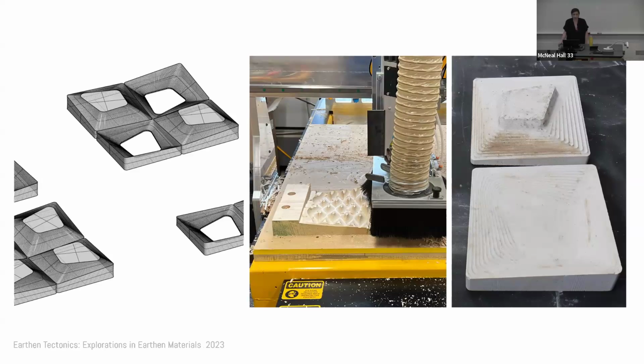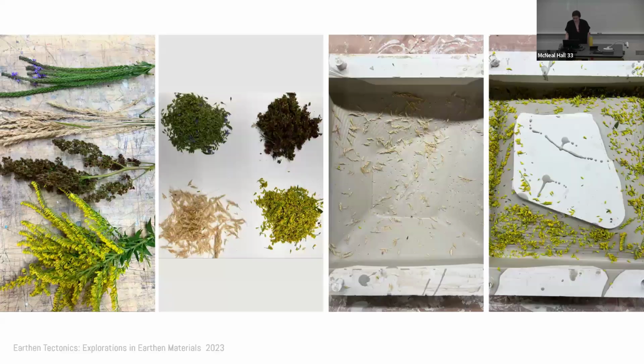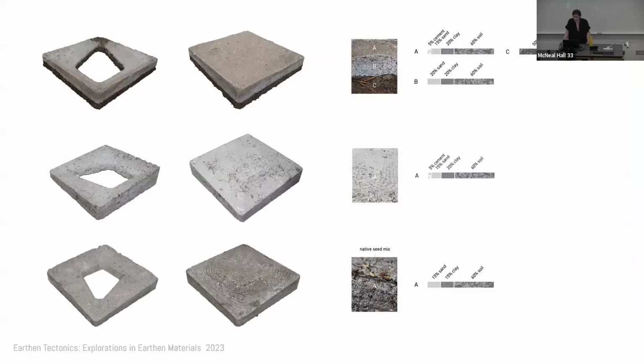We created 2 forms, concave and convex, thinking about how they might collect and shed water. We modeled them in Rhinoceros, milled the negative forms in plaster, and then poured the slipcast modules and rammed the rammed earth modules. Another very labor-intensive process. We're kind of into that, turns out. We incorporated native prairie seeds into our material mixes, hoping that as the modules degraded into the landscape, they would establish native species in the site. And we experimented with different rammed earth material compositions to calibrate their rate of degradation.